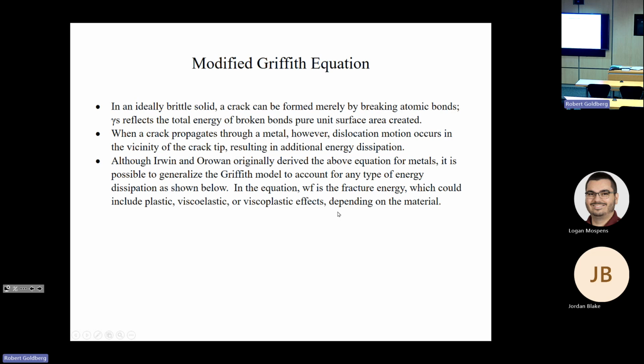So in an ideally brittle solid, a crack can be formed merely by breaking the atomic bond. So the gamma S is the total energy of broken bonds per unit surface area created. But when the crack propagates through the metal, you have dislocation motion, which is reflected as plasticity in the vicinity of the crack tip, which results in additional energy dissipation. We don't cover this in this class, but if you ever take a plasticity class, when you get down to the atomic scale, what causes plasticity of metals is the motion of dislocations.